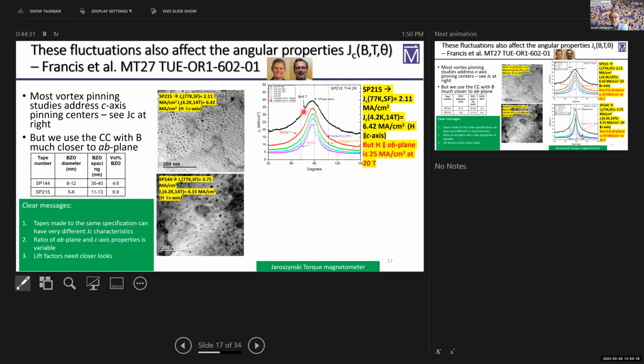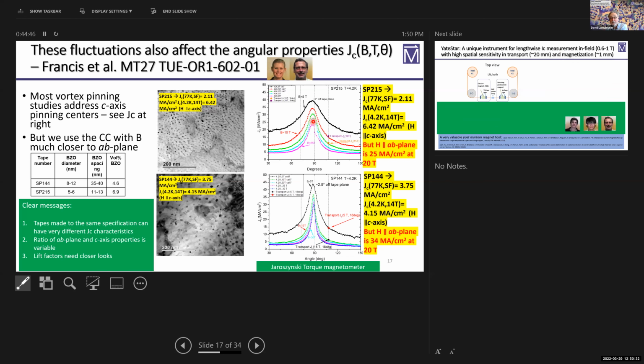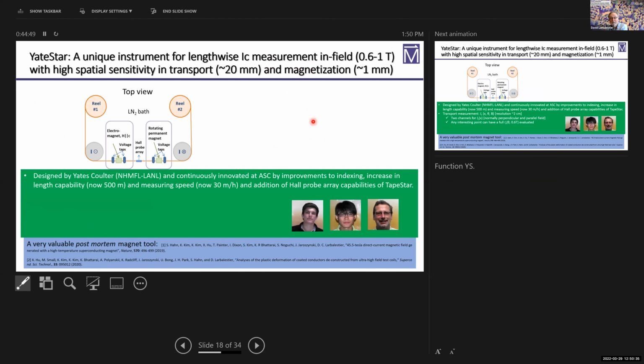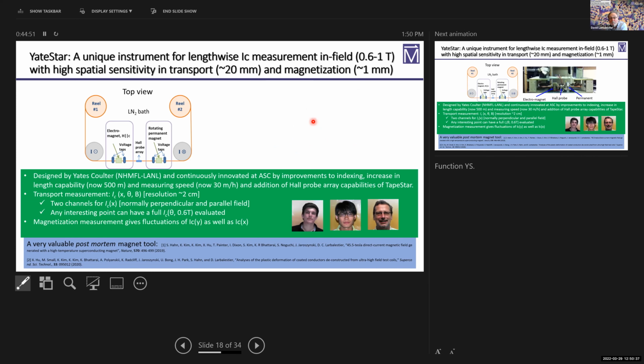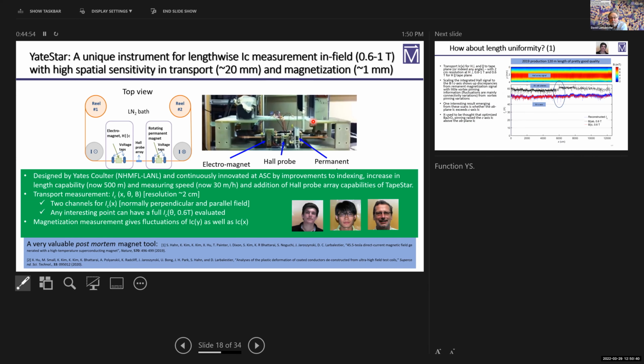But the other difficulty is you get very large torques that develop when the conductor tape axis is not parallel to the magnetic field axis, and very often that generates damage. So this is one of the issues that we're trying to understand. So part of the problem is that with this very complex and in principle highly optimized nanostructure development, everything is beautiful except when it isn't.